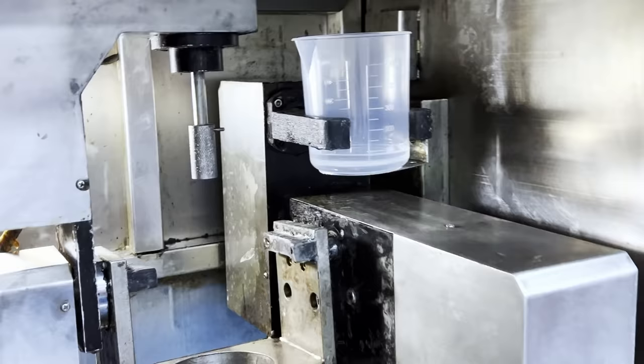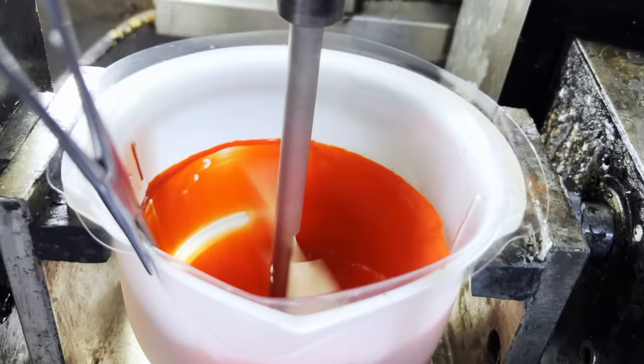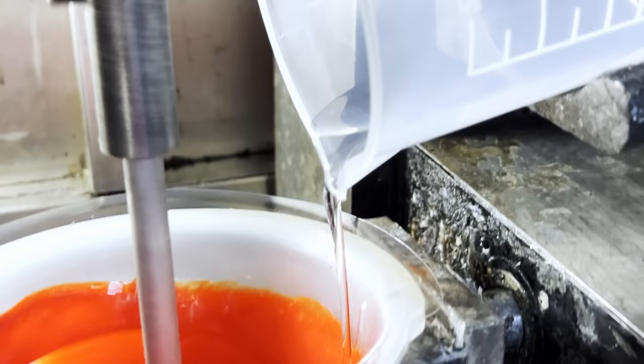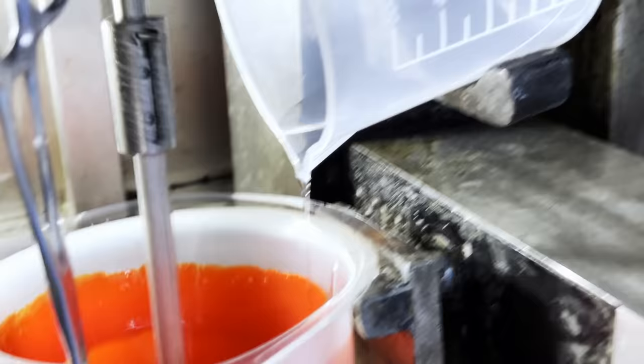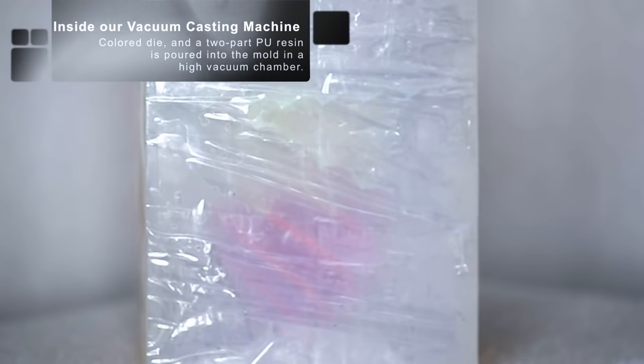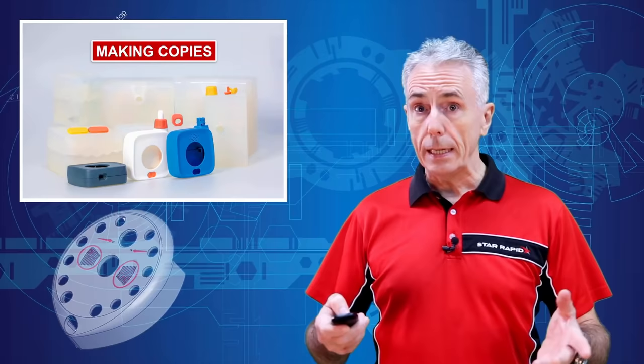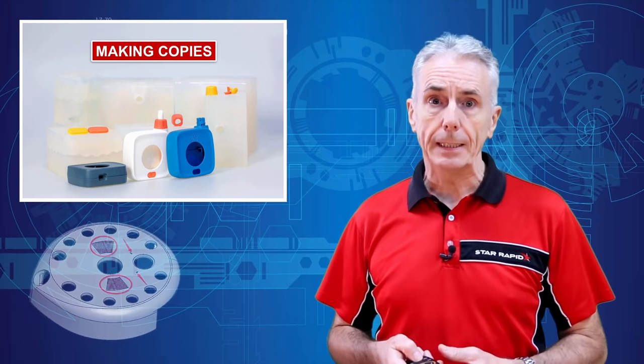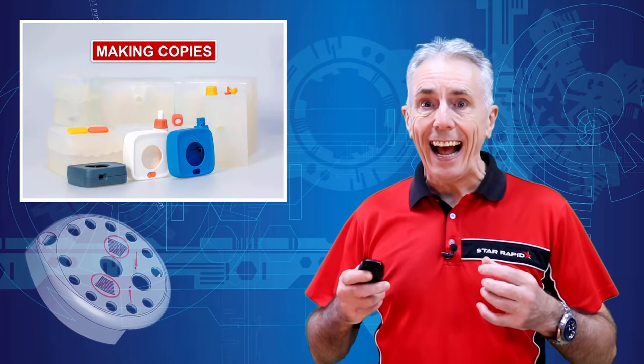Now we are ready to pull a vacuum. With the door shut, we start the vacuum pump and degas the resins, which needs about ten minutes. Then we pour one cup into the other, stir for a little longer, and then we're ready to pour. The two resins are poured down the funnel, into the tubes, and then into the cavity. Once resin comes up the vents onto the top of the mould, we're ready to release the vacuum. Any bubbles that were still in the moulding then collapse to about one fiftieth of their vacuumed size, and the gas in the tiniest bubbles often gets reabsorbed back into solution. That minimizes porosity in the parts, and that is the real reason for the vacuum.